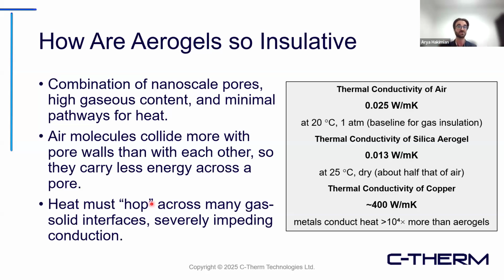So what they're really good at is, of course, reducing that heat transfer. And actually, there's a unique property here, the Knudsen effect, which is related to the fact that when the air or gas present in those voids is confined in extremely small spaces, you actually end up having a net decrease in thermal conductivity compared to even that of just pure air, which is somewhere around 0.02 watts per meter Kelvin. So you can see that the aerogel actually has a solid mass to it, but results in a lower thermal conductivity than air alone. And to compare that to the classic opposite end example, copper has a thermal conductivity of 400 watts per meter Kelvin. So we can see the order of magnitude differences here in the range of performance from something very insulative to something quite conductive.